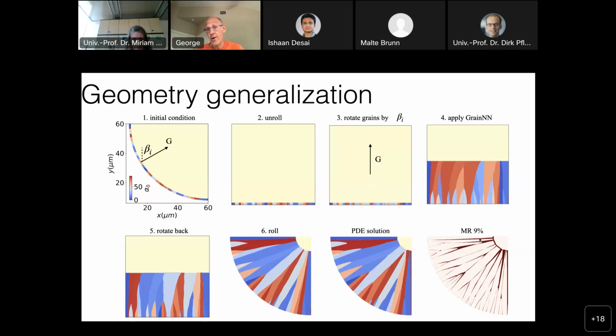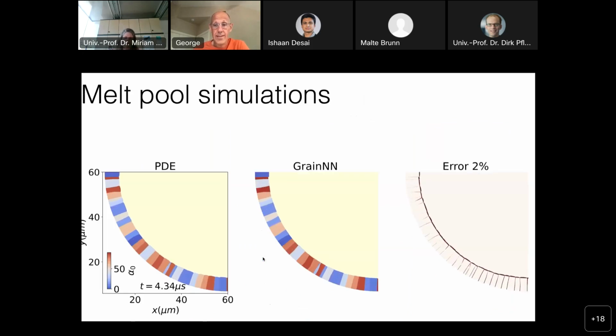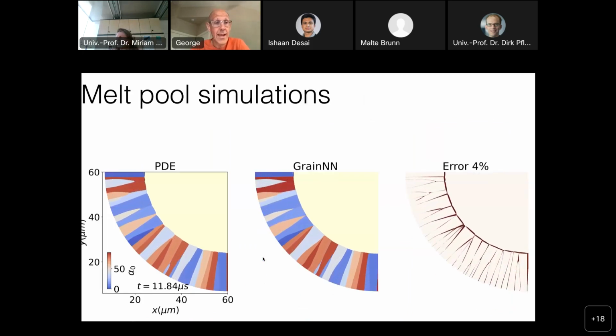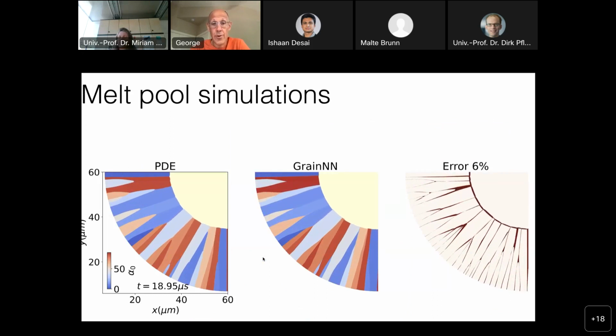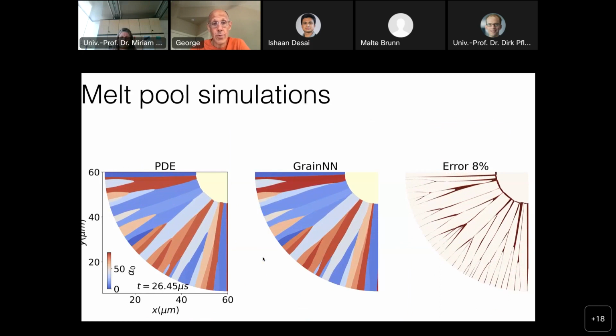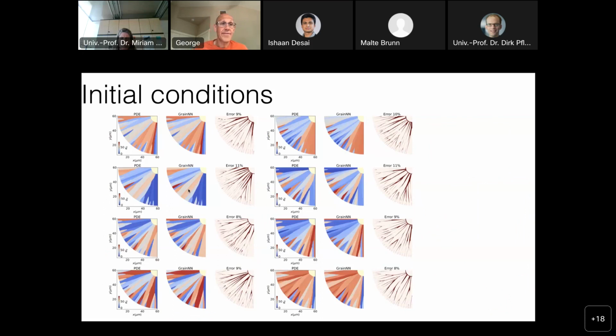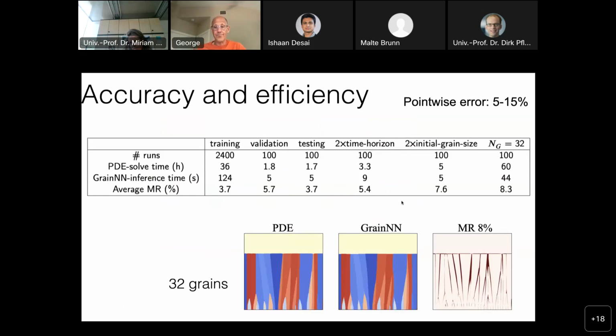And you can see here the error is about 9%. So we never trained for this configuration. And that's the simulation I showed in the opening slide, in which we now use the neural network in order to predict the microstructure. And these are different samples for the same GrainNN. We sample different initial distributions of grains, and you can see the error hovers around 9 to 10%, the point-wise misclassification error.